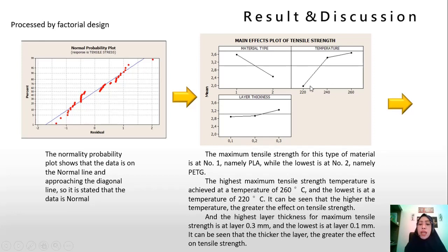and the lowest is at a temperature of 220 degrees Celsius. It can be seen that the higher the temperature, the greater the effect on tensile strength. And the highest layer thickness for maximal tensile strength is at a layer of 0.3 millimeter, and the lowest is at a layer of 0.1 millimeter. It can be seen that the thicker the layer, the greater the effect on tensile strength.